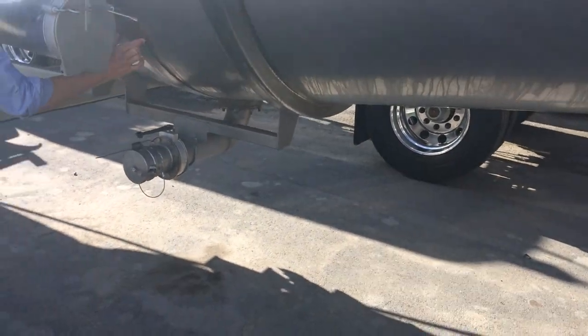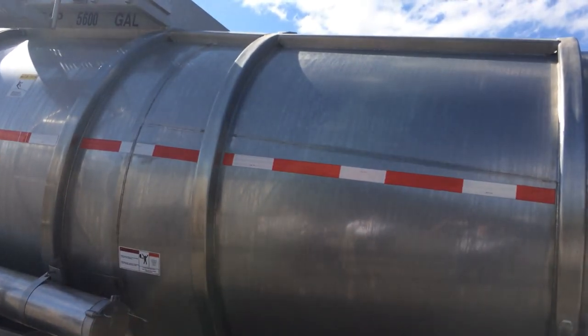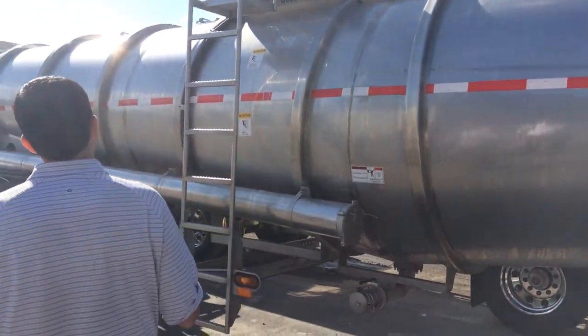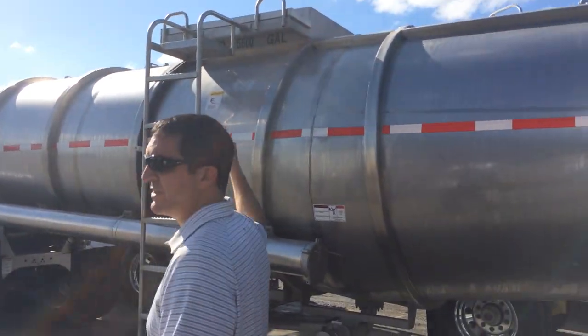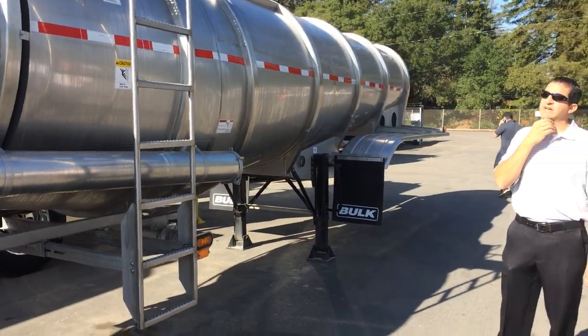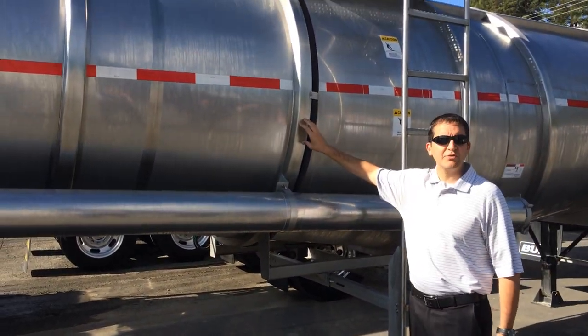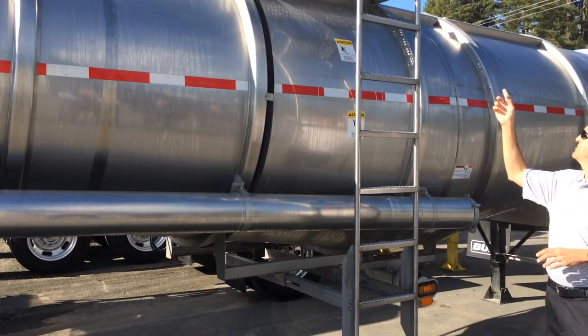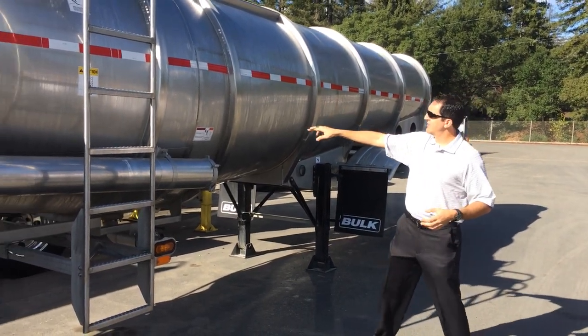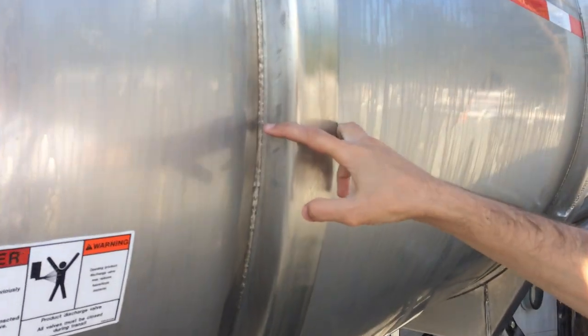On some of the deeper drops, we put channel stiffeners on each side just to support the weight. This is a 5,600-gallon trailer, and the product is pretty dense and heavy. There are multiple variations on walkway design; this is a standard 3 o'clock walkway, and we can do a collapsible type as well — it depends on where the customer is going. We actually roll all the C-channel rings in-house, put the closures on, and they alternate all the way down the trailer to offset possible harmonic balance. It's a manipulated weld that reduces barrel-to-ring fatigue.